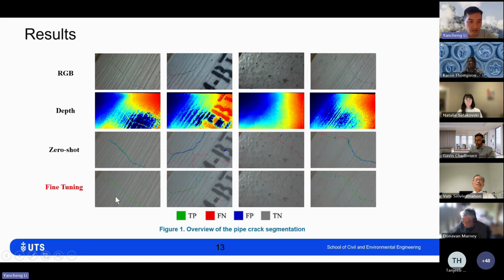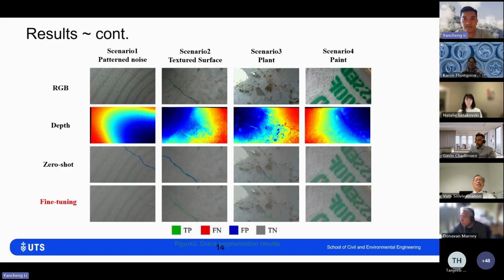So we fine-tuned the algorithm, and we are able to really nail down the crack length. I'll show you the stats very soon. We also selected different scenarios. We intentionally put in some plants and grass to create disturbance. We also put some water somewhere, though I don't think we show the water mark here. You can see from all these scenarios that we are able to detect the crack quite successfully. Sorry, because it is a very thin crack you can't see much, but I will give you some data that you can see very clearly.